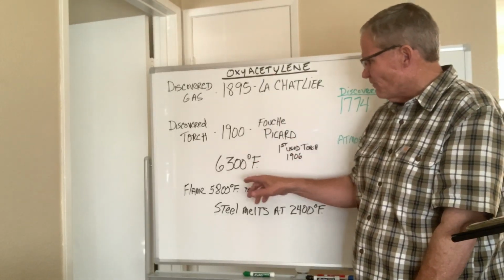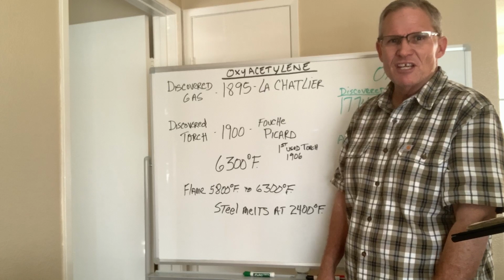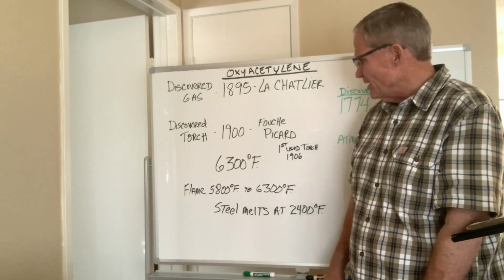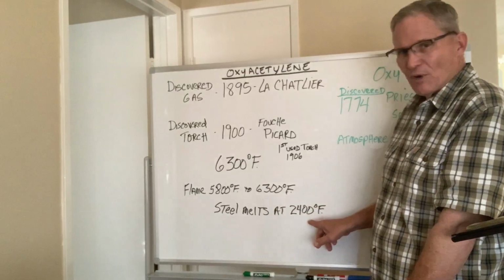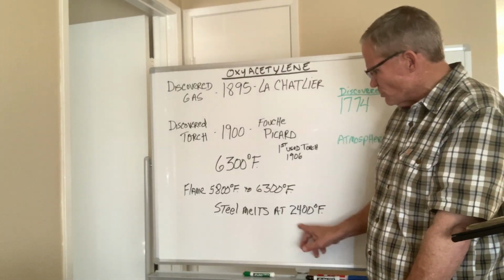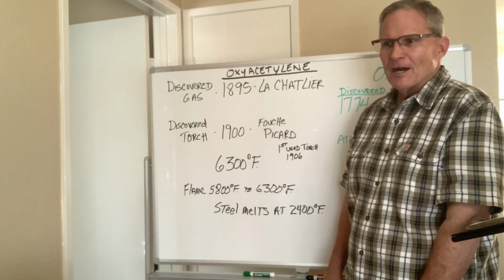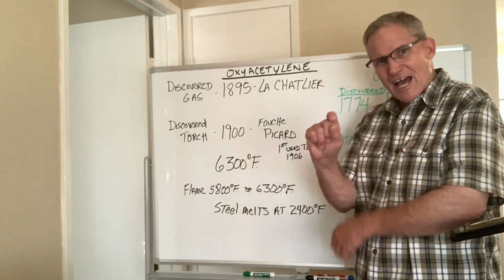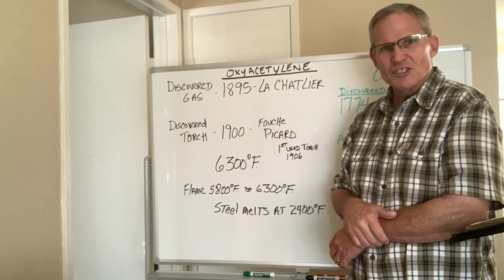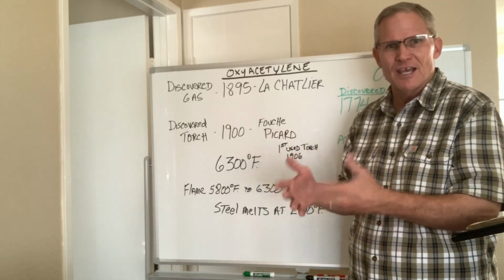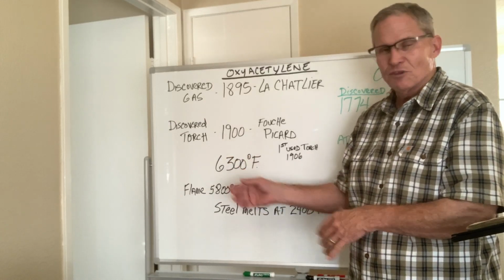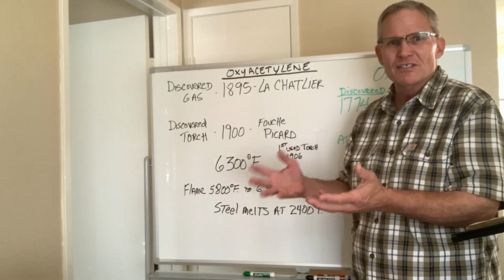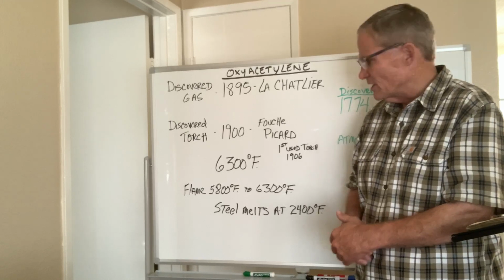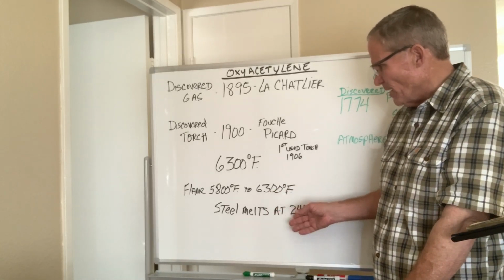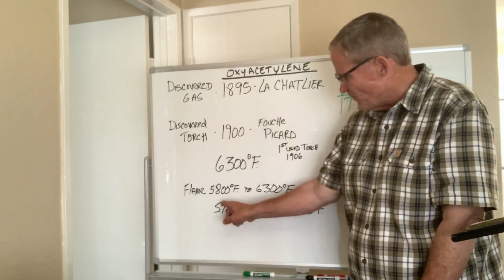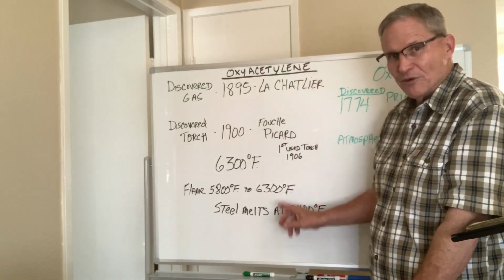But the oxyacetylene flame itself reaches 6,300 degrees Fahrenheit. And the metal that we're using tonight melts at around 2,400. So we shouldn't have any issues with heating it up enough. The only thing that would vary this is the actual thickness of the metal itself. Obviously if you have something thicker, it's going to take more time for this 6,300 to heat it up. And the thinner that it is, the quicker it's going to warm up, and you're going to be able to melt it. The oxyacetylene flame varies from 5,800 to 6,300.